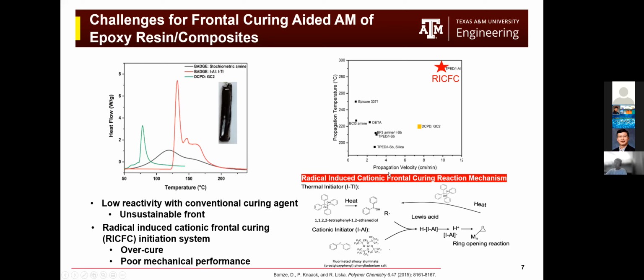And then we can see here the propagation velocity is very high compared to DCPD and other traditional curing agents. However, the problem here is the propagating temperature, the temperature at which the polymerization occurs, is very high, so that the resulting material is turning dark, which means there's decomposition happening due to the high temperature, and as a result, the mechanical property is not desirable.